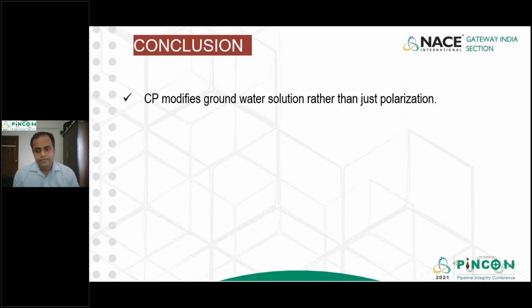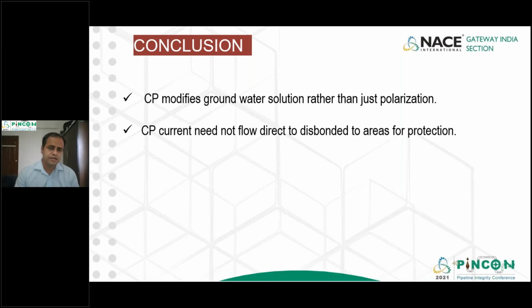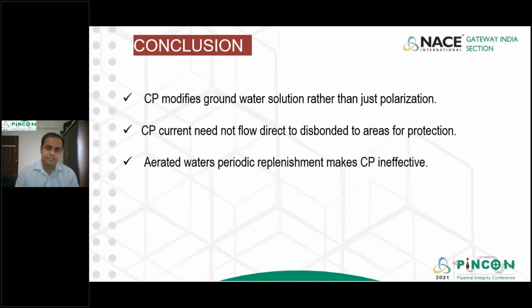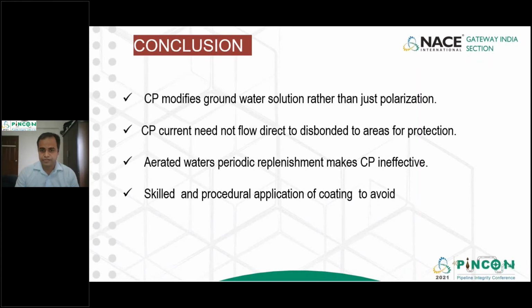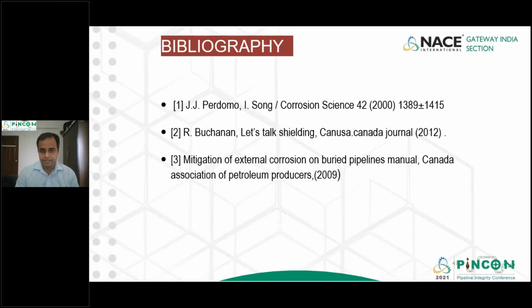I fully feel that the audience will agree with me that the CP modifies groundwater solution rather than just polarization. CP current need not flow direct to the disbonded areas, but it can still protect the areas. Aerated water's periodic replenishment makes CP ineffective because of the seasonal variations. And finally, skilled and procedural application of coating should be done to avoid any damages.